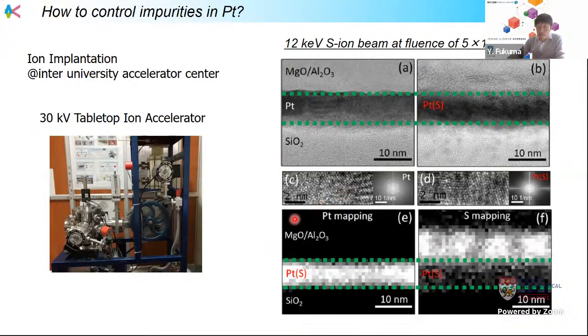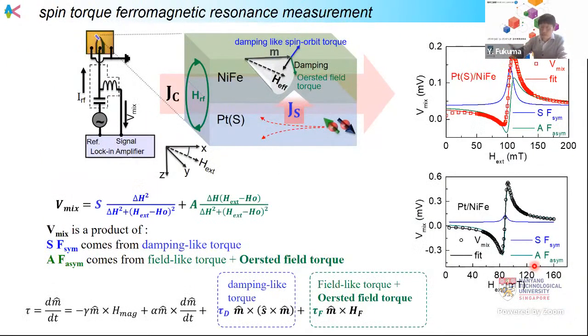Also, we did energy-filtered electron energy loss spectra of the platinum and sulfur. What we can see here is the platinum layer. Then this is the sulfur element mapping. More sulfur is implanted in this oxide layer, but we can also see sulfur ions in the platinum layer. From this picture we can estimate around 10% impurity in here. Then we remove the oxide layer.